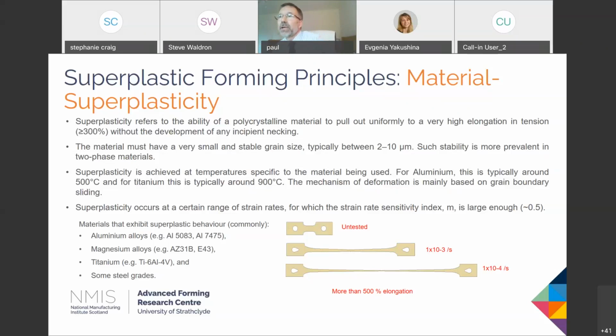Now, of course, these very high elongations are not of too much relevance in an engineering setting. In most superplastic forming operations, the maximum elongation that we would see in a part would be 100% or less. Because clearly, if you start off with a sheet of material that's a couple of millimeters thick, by the time you've stretched it for about 100% extension, the residual thickness of the material is starting to get so thin that it's of no real engineering use.